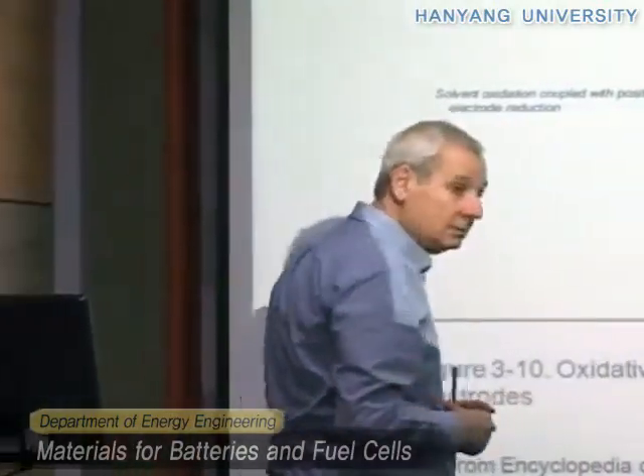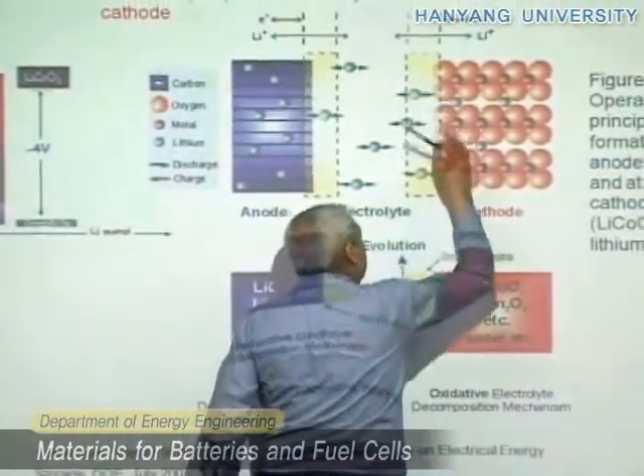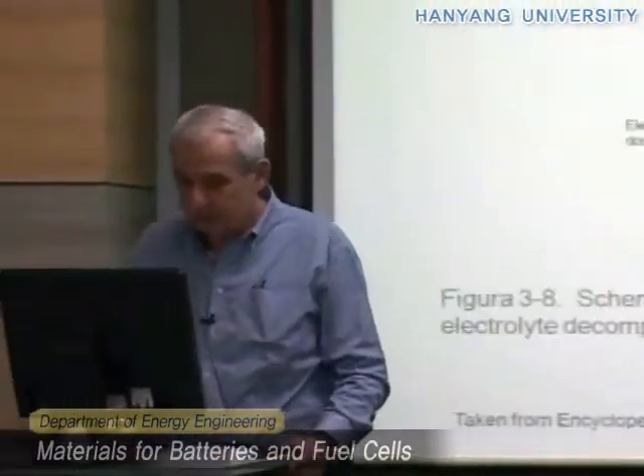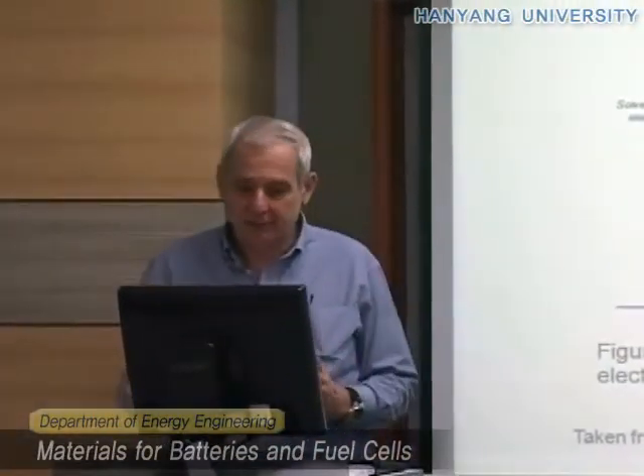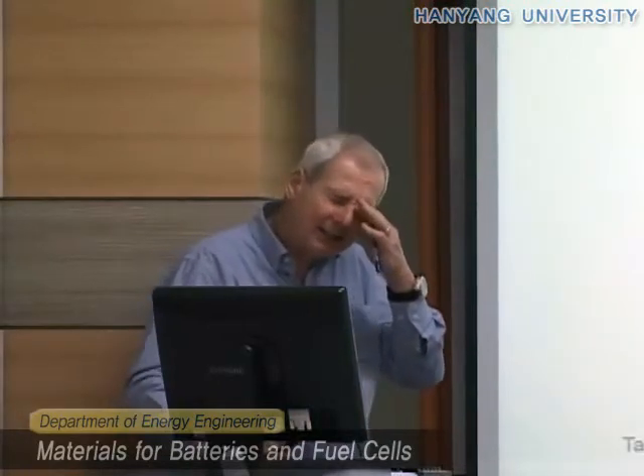This is the reason why these films, since they don't allow the transfer of electrons, block the decomposition. But the decomposition always occurs at the beginning, with the formation of gases and other things. As I mentioned before, battery producers when they make a lithium-ion battery always have to charge and discharge the battery for two or three cycles in order to eliminate all the gas produced by the decomposition of the electrolyte. Then they can seal the battery.